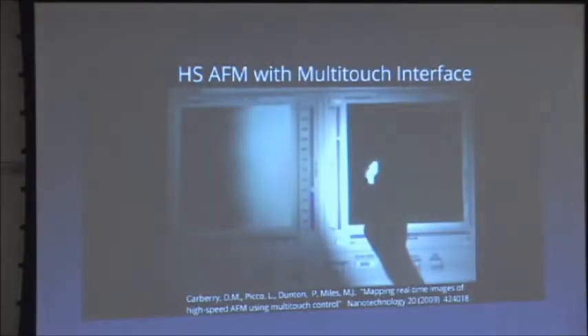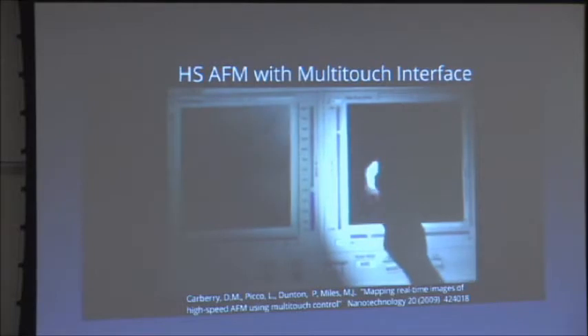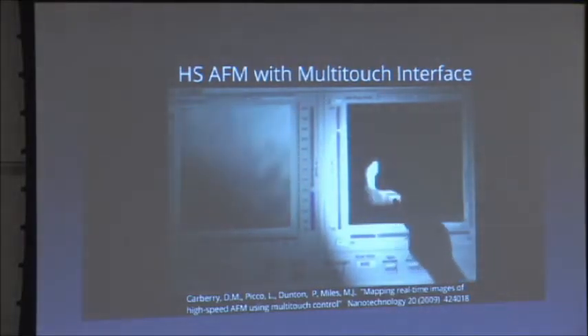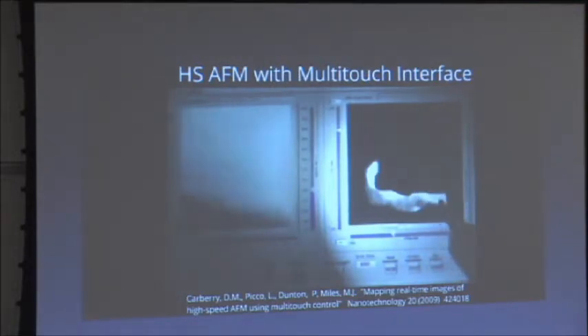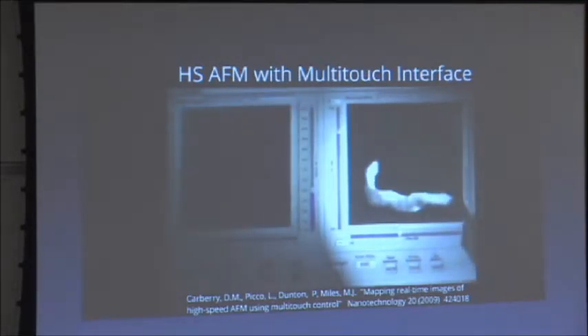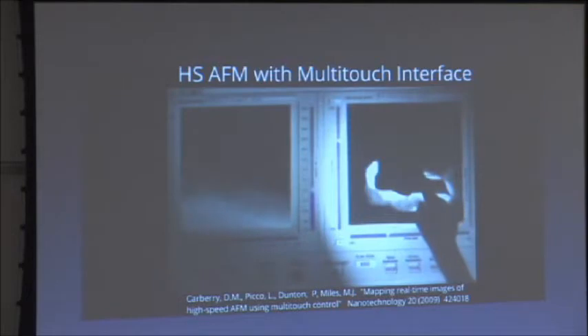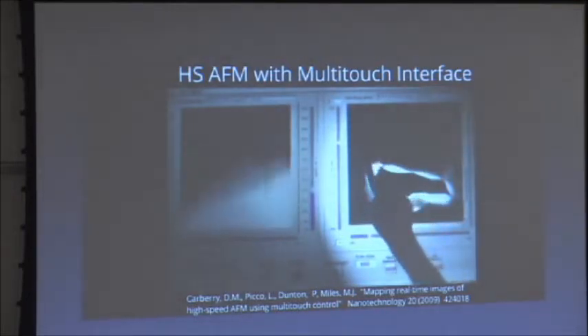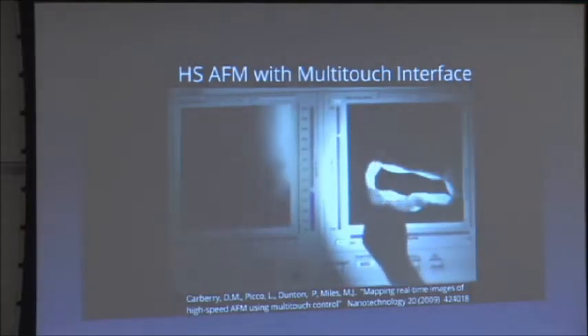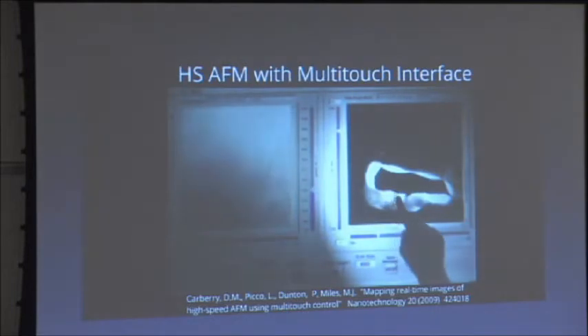And then here is a use for it. This is tracing around a chromosome, one of those human chromosomes. On the left, we're just keeping the interface. So this bit is bright and this bit is dark. We're just at the edge of the chromosome. So what we're doing is tracing around, making a mask so that we can set different parameters inside and outside. So we've got the hard surface it's sitting on, but we might want to change the feedback and the forces we're applying on the inside where the chromosome is a lot softer. So we can draw around it and make a mask where we automatically change the settings.